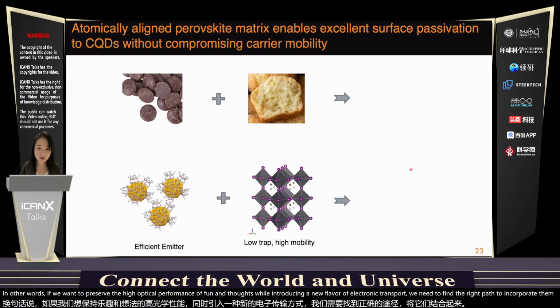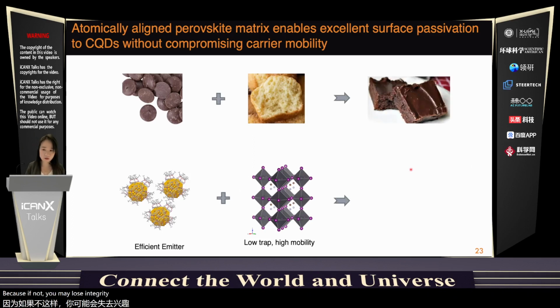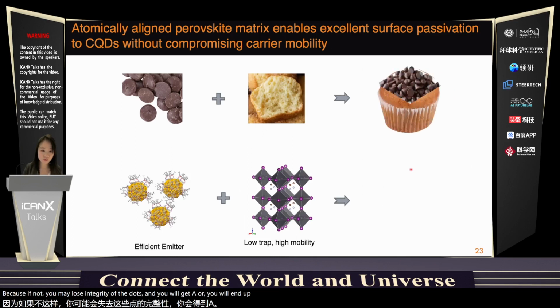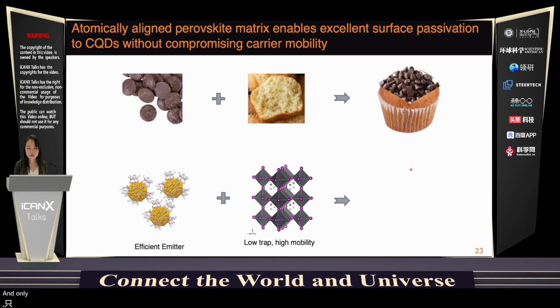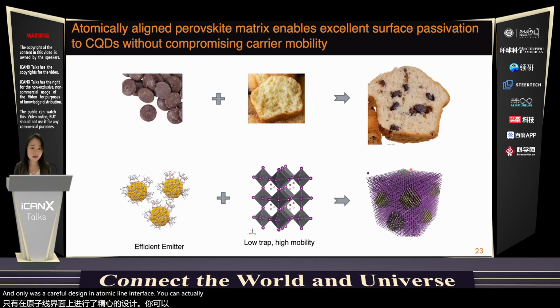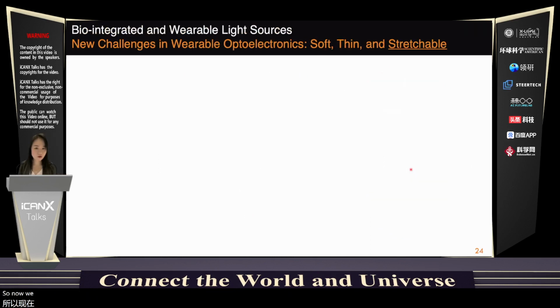Because if not, you may lose the integrity of the dots and you will end up with phase-separated quantum dots and perovskite. And only with a careful design and atomically aligned interface can you actually get the best of these two components. So now we have overcome the efficiency of quantum dot LEDs.